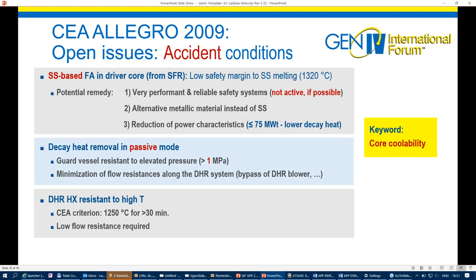Open issues in accident conditions come mainly from the stainless steel based fuel assemblies. The peak cladding temperature in any kind of accident must be limited to temperatures well below the melting temperature of the stainless steel, which is quite a technical challenge. So the key word today of the safety of Allegro is to ensure core coolability.